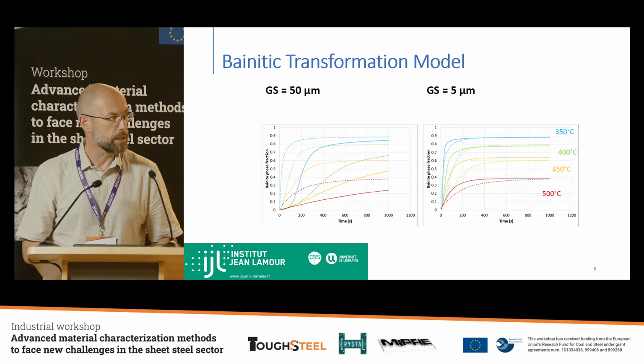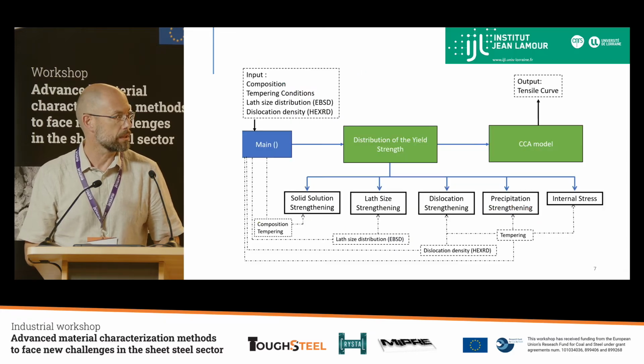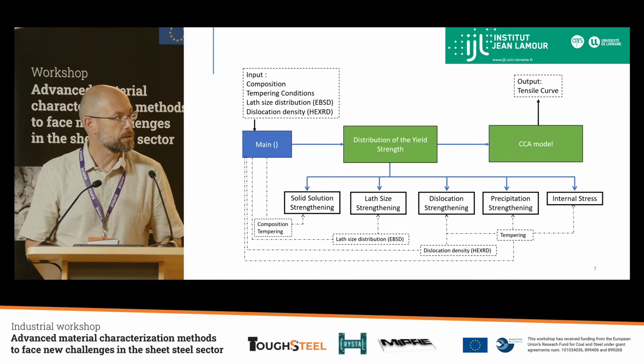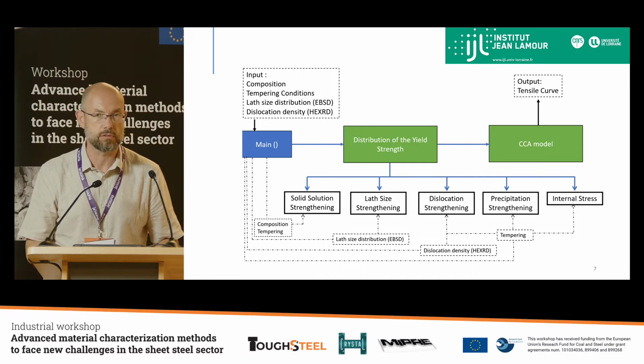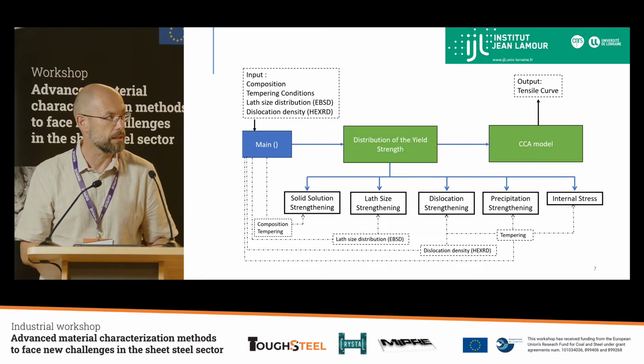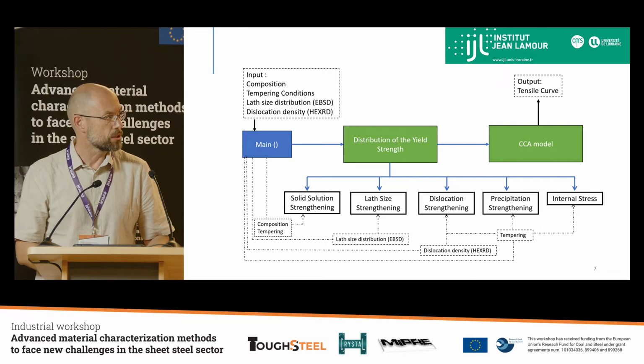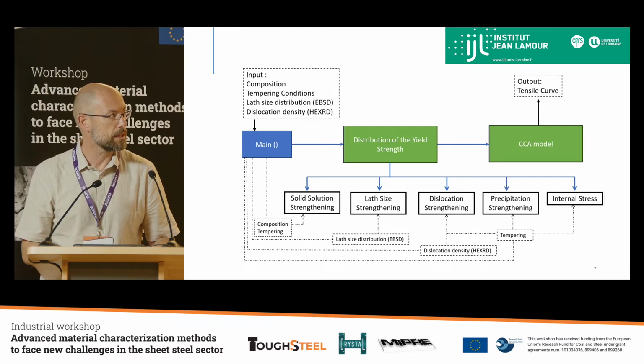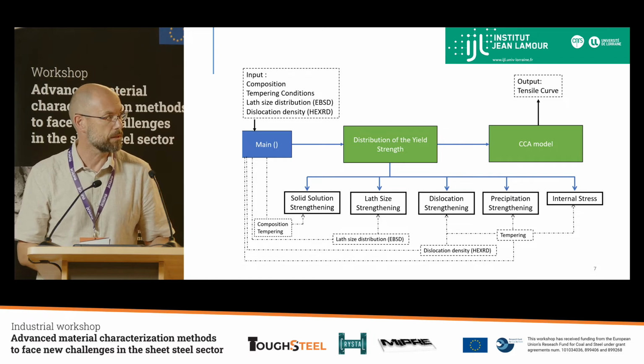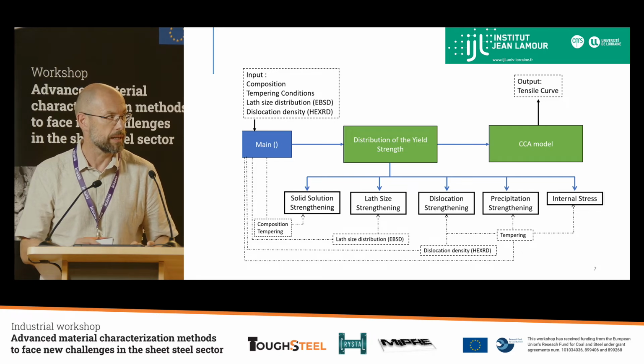So we also introduced the martensite transformation and the tempered martensite transformation model in order to implement them in a CCA model, to introduce the effect of the microstructure on the final mechanical properties that we are going to have in terms of tensile properties. So from basic experiments or basic microstructural parameters as input, we can get a result for the tensile or strength properties of the steel.